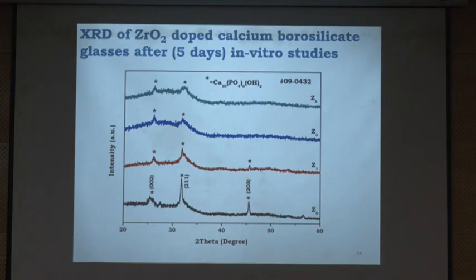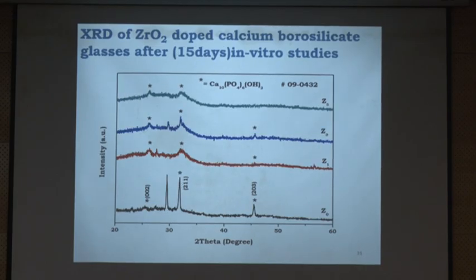So what happened here? There is a leaching of ions between the metal and the SBF. Because of the leaching of ions, the nucleation centers and then the growth process, slowly as time progresses, the layer has formed, and we are confirming it by means of XRD. This is the first step to confirm whether the metal is active or not. Similarly, after 15 days, we recorded the XRD. You can see the intensity of the peaks has increased compared to the previous case.